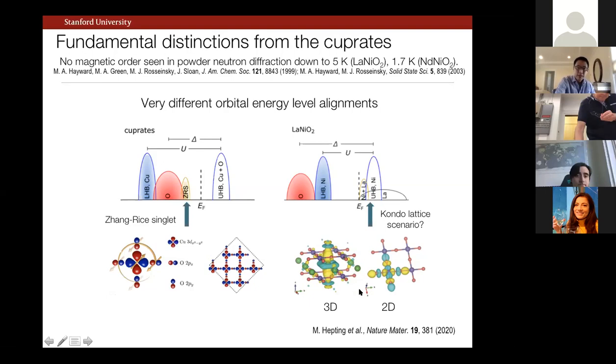And so how they look, from this paper here, what you can see is that indeed the nickel states look very much like the Zhang-Rice singlet, but with much smaller amplitude, as we'll find in a moment, right? Even though we're several electron volts above, there's still quantum mechanical hybridization. We have states like this in terms of a real space kind of Wannier picture. But again, what's very different from the cuprates is this hybridization with the rare earth states. And so something that has a much more three-dimensional character. Okay.